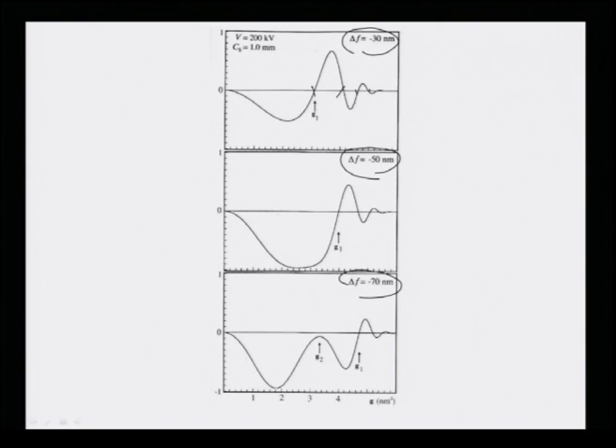And as you go from minus 30 to minus 50, the g1 value shifts to the right side, so more information for the lower spatial frequency ranges can be transferred to the image plane. But as you increase delta f to, say, minus 70 nanometers, you can see that g1 actually never reaches the zero axis value, and g1 is coming at a higher value, but g2, another kind of spike, comes into the picture, which is restricting the transfer function to a much lower value of g which can be transferred to the actual image. So these are the two effects of CS and delta f.